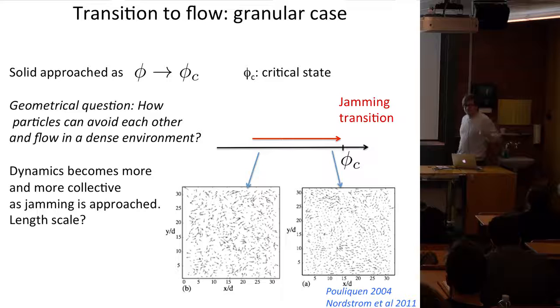All right, so now what's the physics as you lower this angle and you approach the solid phase? You have a problem of crowding, so the system is denser. And one question you can ask is how can particles rearrange in a very dense environment? And that's something that you can easily observe experimentally. That's what's done by Pouliquen. You have this layer of sand and you decrease the angle. And what you do is that you take a video from the top and you look at the velocity field of the particles.